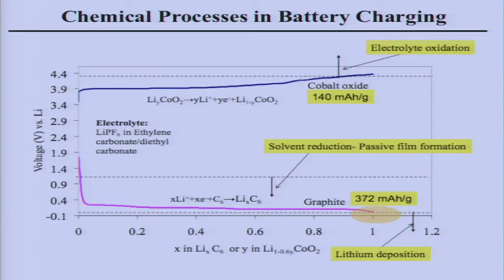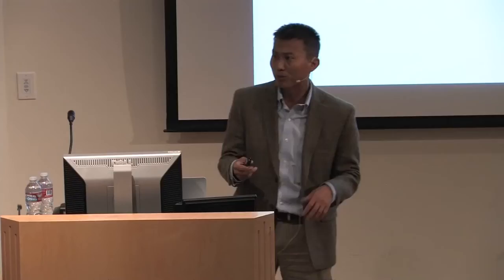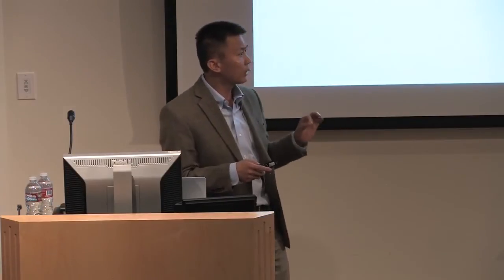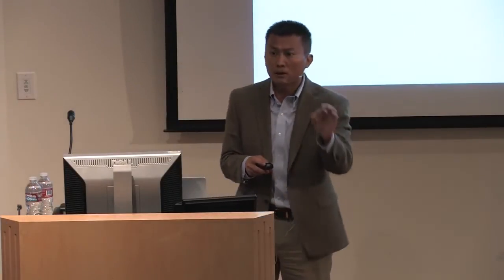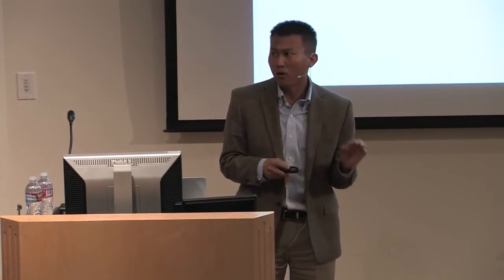On the positive electrode side, you take out this lithium, this is the voltage plateau, and then when it rises to roughly 4.3 volts versus lithium, it starts to oxidize the organic electrolyte. You don't want that oxidation to continuously happen, so you want the surface to be self-passivated. If you don't do that, this oxidation will keep happening and produce heat. You heat up the lithium cobalt oxide, that further increases the reaction, and then heats up even more. And the battery can also catch fire this way and cause an explosion. So it's quite amazing. The battery industry is doing a great job in making batteries safe. When you charge, don't overcharge.